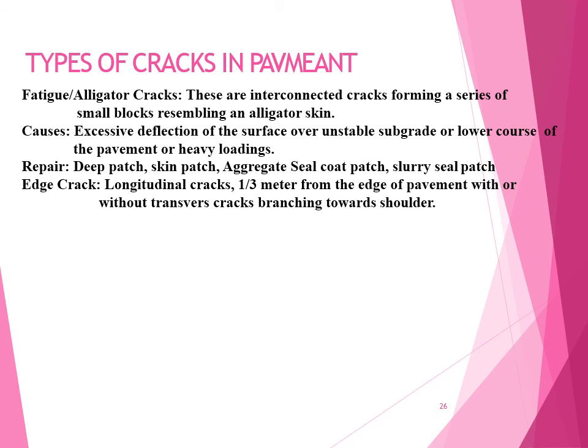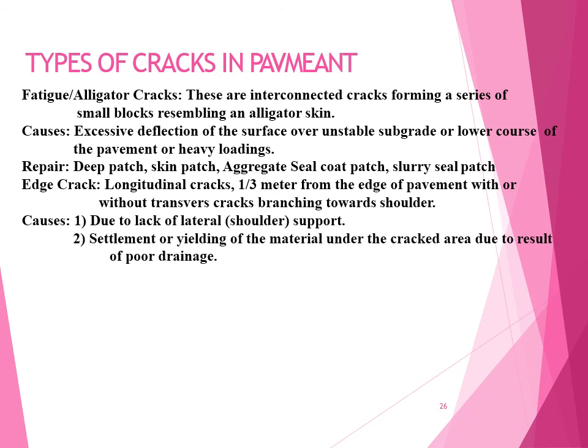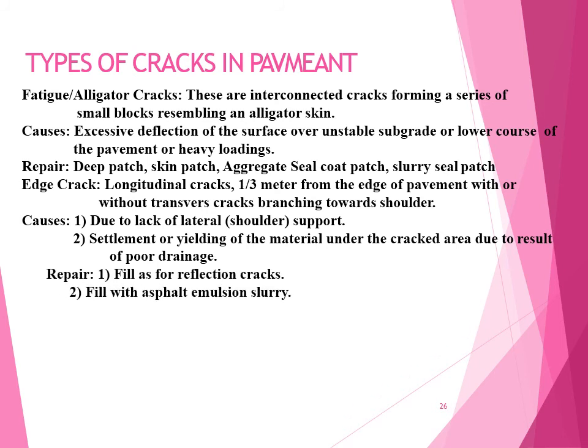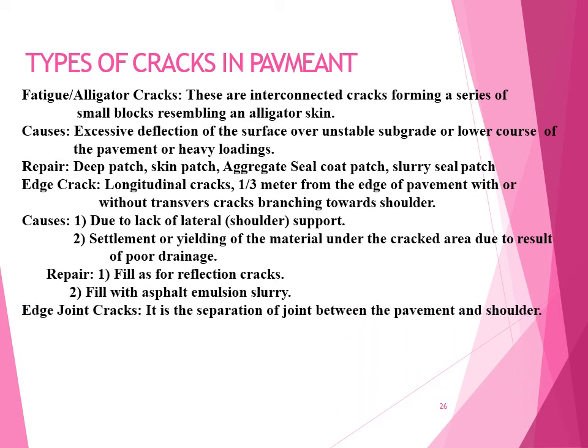Edge cracks are longitudinal cracks located within one-third of a meter from the edge of the pavement, with or without transverse cracks branching toward the shoulder. Causes include lack of lateral support, settlement or yielding of material under the cracked area due to poor drainage. Repairs include filling as a reflection crack or filling with asphalt emulsion slurry.